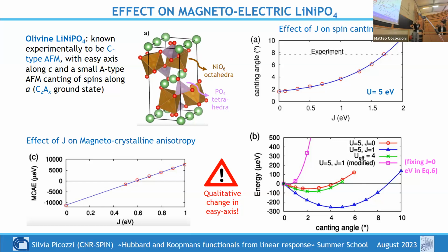Just a quick follow-up for myself on this. According to your experience, in order to get these different magnetic configurations or spin orientations, do you just rely on them being a stable state, or do you have to impose constraints? Yeah, so you usually add a local magnetic field. There's a penalty function that keeps your spin from deviating from the one you want.